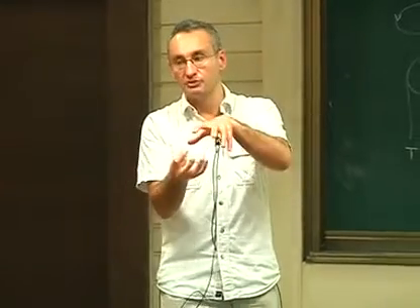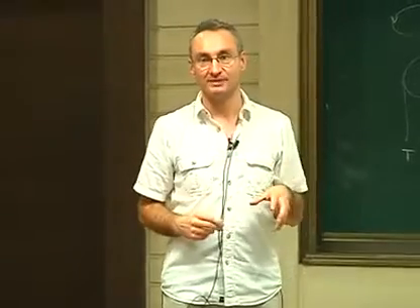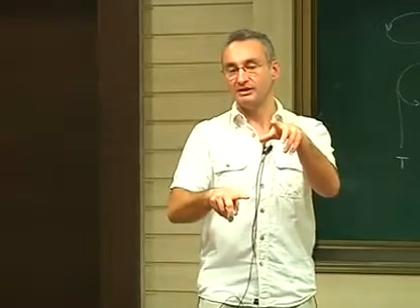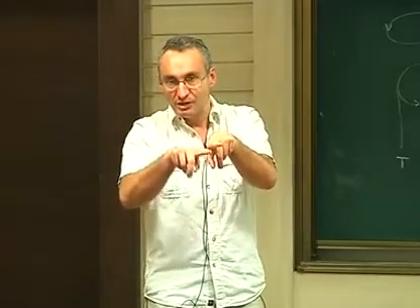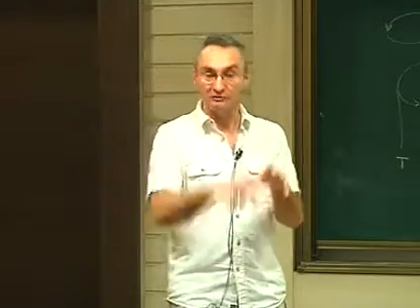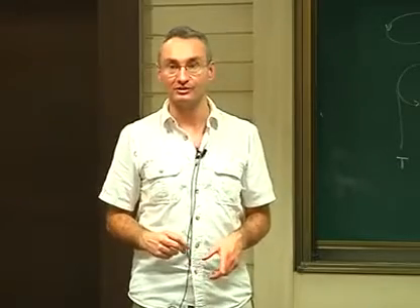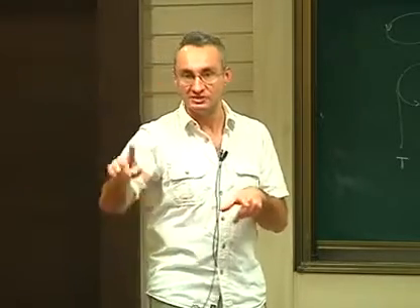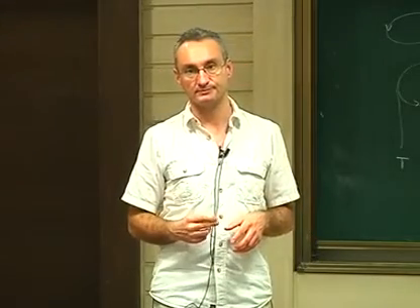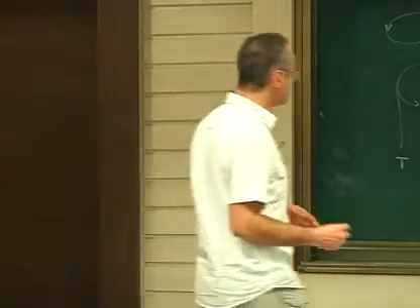To avoid that, people put some non-dimensional size of the box, so that it will make many turns before coming back in the same plane. That's the way to do it. But then, if you make many turns to come back in the same plane, you will have a large probability to have two planes very close to each other, so then you will create dipoles, which is worse. So either you have a softening, when you have no change of your plane, or you have dipoles, which is very strong hardening. So periodic conditions are not good for a single slip system. I would prefer to have a bigger box to avoid this self-annihilation, typically. We will not be able to go into plasticity with that. Yes, okay? I like your question, it's nice.